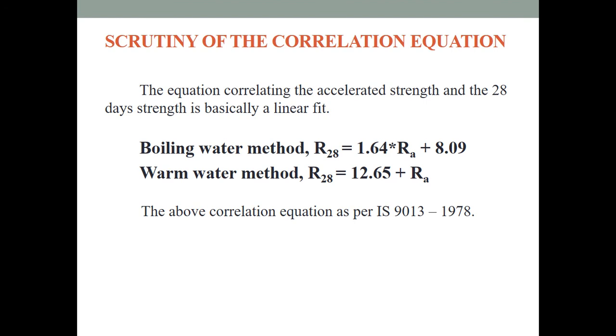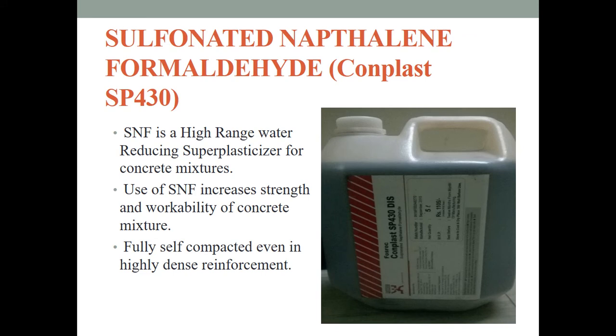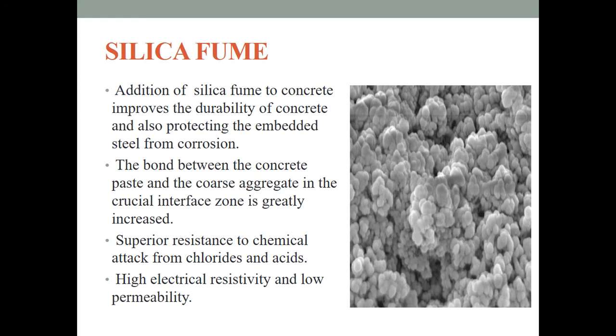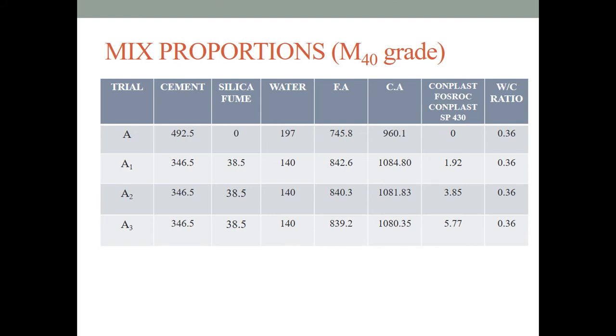This is the scrutiny of the correlation equation, which means the prediction of 28 day curing strength from 24 hour curing strength by applying the correlation equation. Boiling water method: R28 equals 1.64 times RA plus 8.09, where RA is the obtained result, that means the compressive strength or split tensile strength result obtained within 24 hours after testing. Warm water method: R28 equals 12.65 plus RA. Conplast SP430 is the superplasticizer which I used in my project. Silica fume has been used as a partial replacement of cementitious material. So this is my mix proportion for M40 grade concrete.